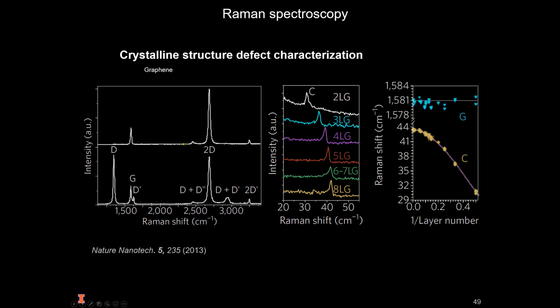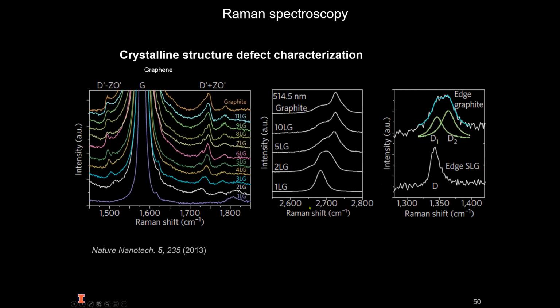And then here, several different layer thicknesses as well. The number of layers will also significantly change the Raman spectrum of graphene, and several other 2D materials, so we can use this technique to determine that parameter as well.